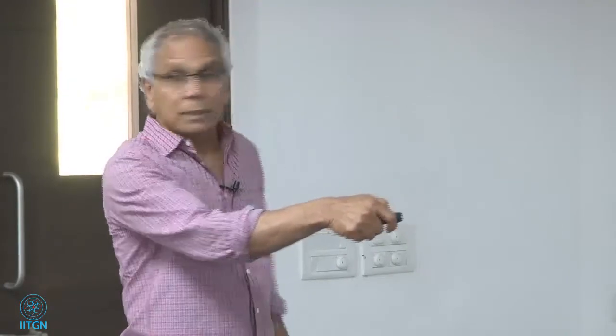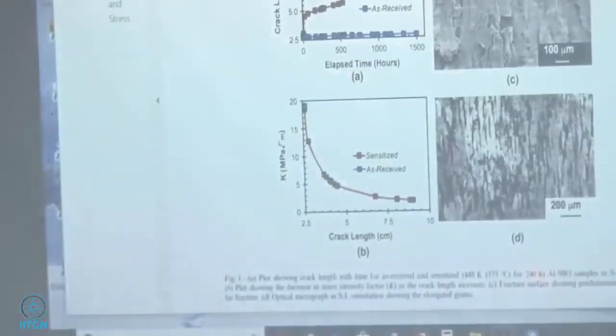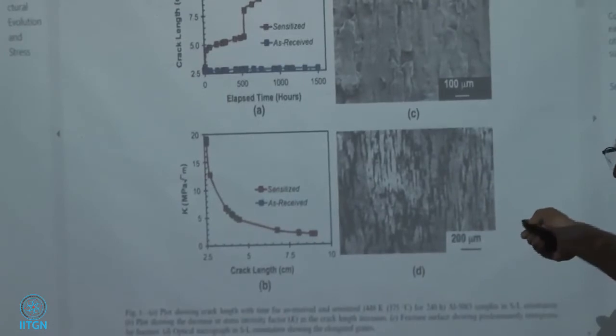Celsius. So if you take an aluminum magnesium sample and do a simple crack growth test, you put it in the machine, put a dead load, and monitor the crack length. Nothing happens in the as received material, the blue ones. But if I now take the aluminum magnesium, put it in the oven at 175 degrees Celsius for 240 hours, and take that specimen and put it in the machine, the crack length starts to rise because there are a lot more grain boundary precipitates. Do you see what I'm saying?